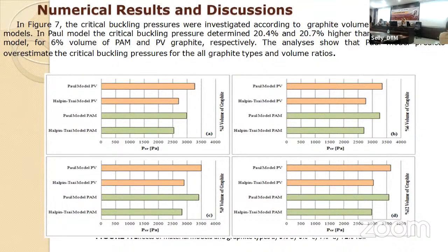In that figure, we can see the critical buckling pressure as the graphite volume ratio changes. In the Paul model, the critical buckling pressure was determined to be 20.4% and 20.7% higher than the Halpin-Tsai model. The analysis shows that the Paul model overestimates the critical buckling pressure for all graphite and volume types.